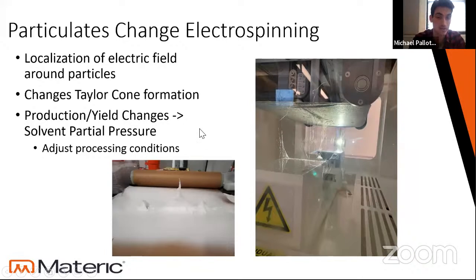And then during the actual electrospinning, there's a potential to run into a number of different issues that we've only figured out by empirically trying things out. The first is localization of the electric field. Again, everything comes down to making sure the solution is uniformly dispersed in terms of the nanoparticles. On a nozzle system, like the Inovenso PE 550, if you don't have a uniform solution being pumped through, and one of your nozzle heads is receiving more nanoparticles and polymer solution than another, you'll start to see discrepancies between the electrospinning, and your electric field won't be dispersed correctly along the entirety of that rod. So you'll have a non-uniform mat being created, and in some cases, you might not even have nanofibers forming.